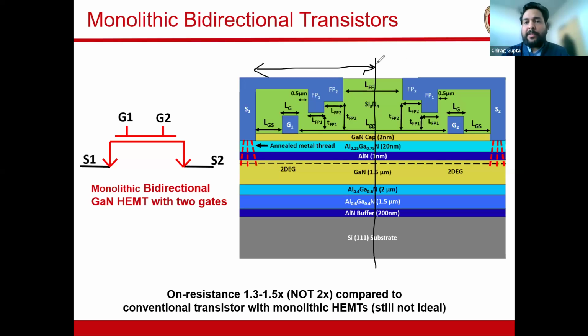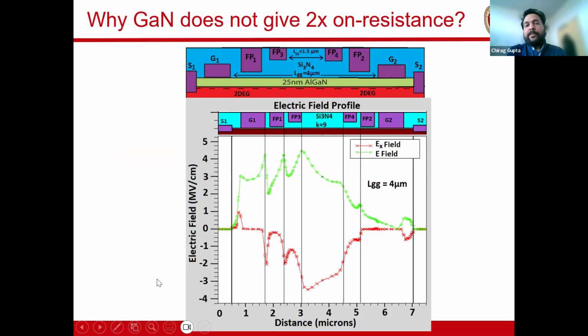And part of the reason is that this region right in the middle is called the virtual drain. In this virtual drain, the electric field and the physics turn out in such a way that it gives you this advantage of 1.3 to 1.5x. This is something that we studied with TCAD simulations, and this is what I'm showing here. If you take a conventional transistor, your electric field starts to decay after the end of the field plate. However, the presence of the field plates on the other side, in this particular case field plate number 4 and field plate number 2, allows you to keep your electric field a bit higher, and these field plates help in spreading the electric field and allow a little bit of sharing of the voltage on either side.